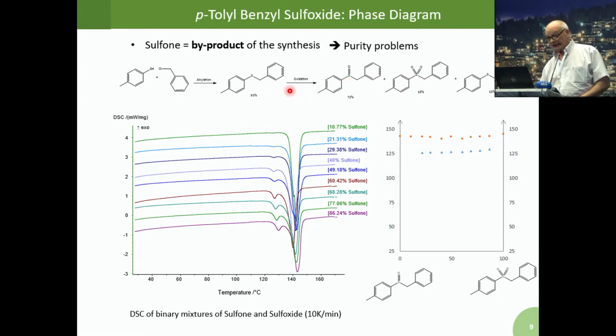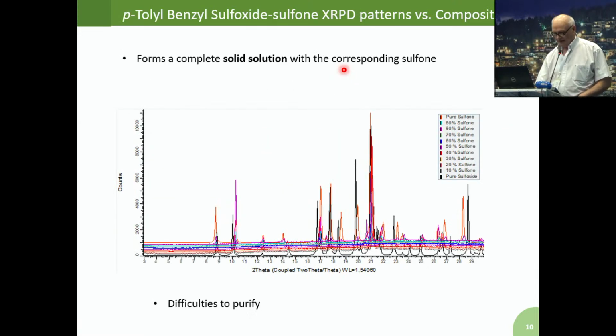But unfortunately, by all the different oxidation agents that we used, we got a mixture actually of sulfide, sulfone, and the sulfoxide. So we have tuned the conditions a little bit so that we got mainly sulfoxide and still sulfide, but with no sulfone. Why no sulfone? Because sulfone can make a complete solid solution with the chiral molecules here. Okay, so the impurity, which has not any intrinsic chirality, can adapt to both enantiomers, to both crystal lattices of the two enantiomers. So we checked that by using X-ray powder diffraction, that we have a complete solid solution.